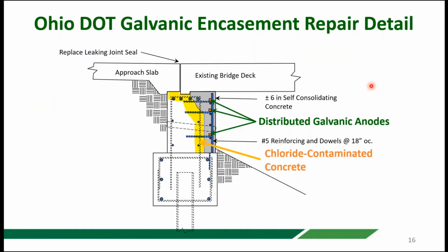The solution that Ohio DOT did, this is a job that was done back in 2005. Basically, I'll show you through a series of pictures, but they essentially removed the existing cracked and damaged concrete that you could see in the previous photograph, and they put a new 6-inch thick layer of self-consolidating concrete over the entire face of the abutment with new reinforcing steel and dowels. And they specifically put in distributed galvanic anodes, illustrated here, into that refacing.